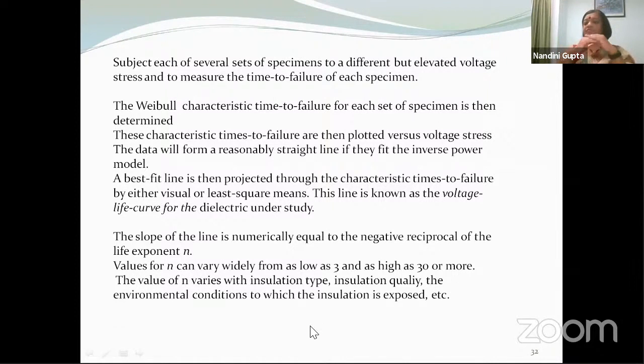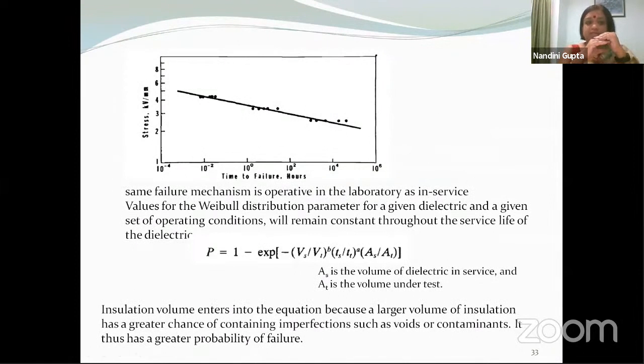significantly. Once you have determined the value of n and obtained the best fit data, what you can do is extrapolate. So for example, you have data which gives you time to failure in seconds or in hours, and with that you can extrapolate data for failure in the range of years or months. But again, as I said, the failure mechanism should be the same.